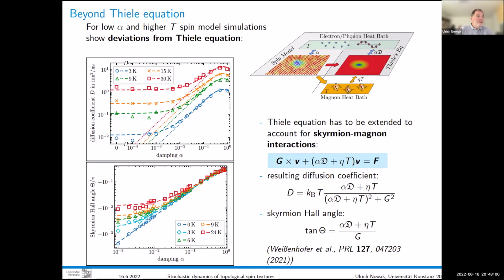This is not only a correction for the diffusion coefficient, by the way, it also changes the Skyrmion-Hall angle. So with this theory, we would forecast the Skyrmion-Hall angle should depend on temperature, which it does not otherwise. I haven't explained what that is, but maybe for the experts. So that is another side result of this simulation. So we would say if you measure Skyrmion-Hall angles at different temperatures, you should get different results. And that is not the usual theory. That would just be this first part without this eta T.